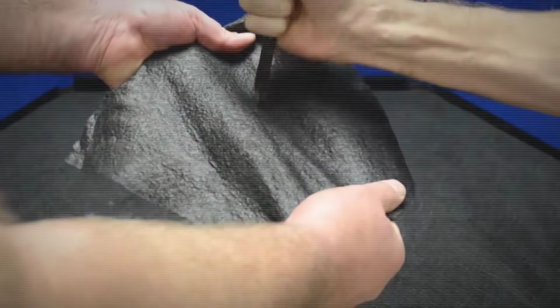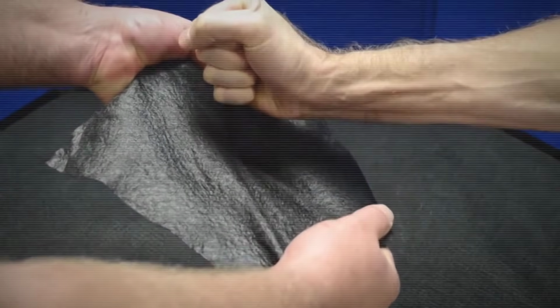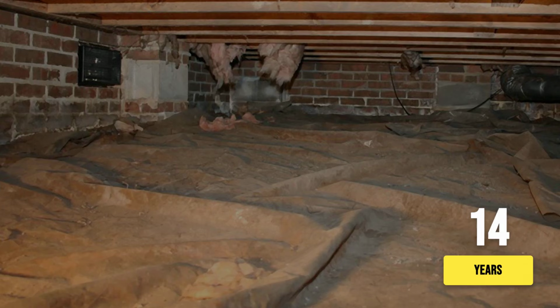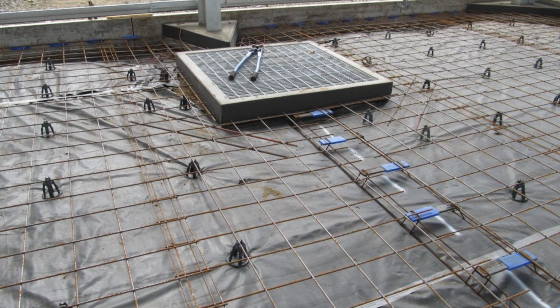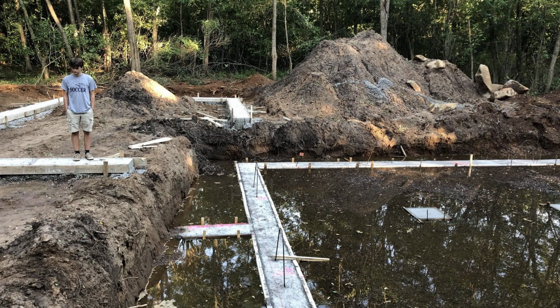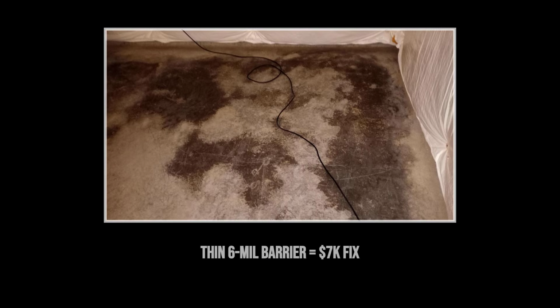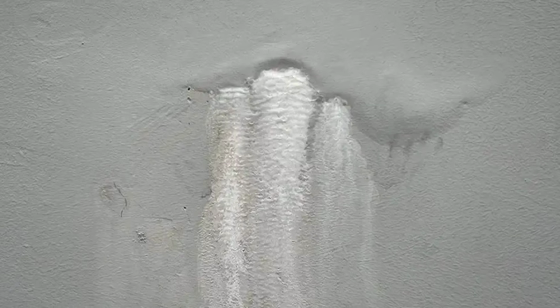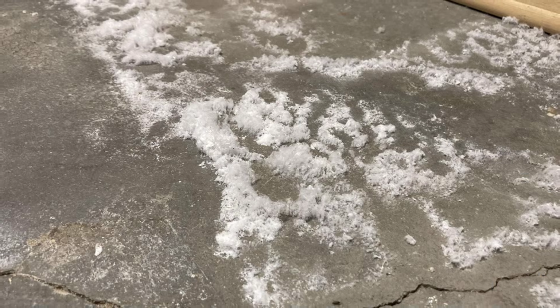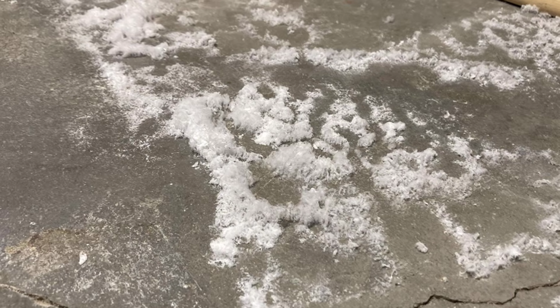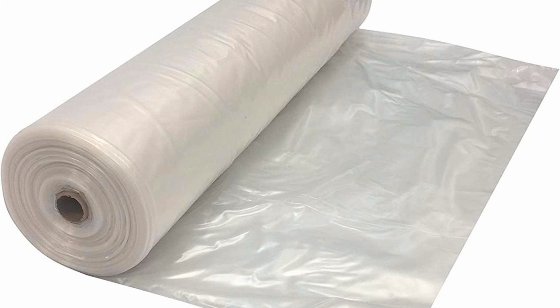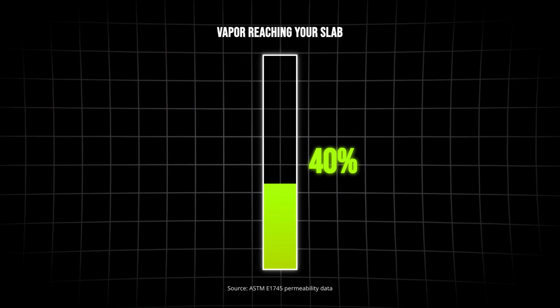However, building science and field data show that a 6 mil barrier degrades within 10 to 15 years. Punctures and pinholes form under hydrostatic pressure, especially in regions with high groundwater, allowing moisture to migrate upward through the slab. Efflorescence, the white crust of dissolved salts, appears on basement walls and floors within a decade. The thicker 10 mil or 20 mil polyethylene, by contrast, resists puncture, limits water vapor transmission by 60%, and maintains integrity for 30 years or more.